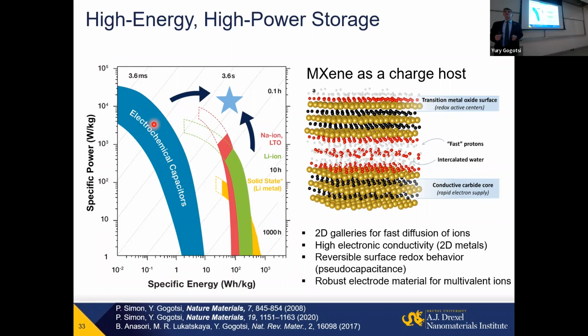So we need materials which are electronically highly conductive. And MXene potentially offers this. They offer electronic conductivity which is orders of magnitude higher. For example, activated carbon used in supercapacitors, which are our fastest energy storage devices, has typically about 100 to 300 Siemens per centimeter conductivity. We can go 2 orders of magnitude better with MXene.